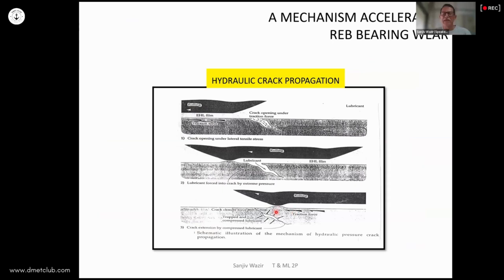But had we been using lubricants to prevent this from happening in the first place, or to extend the time before it happens, then these surfaces are now wetted surfaces, and if sufficient lubricant has got entrapped inside when we are trying to close down that crack, the trapped lubricant might create a kind of hydraulic jack effect inside that crack. The crack might actually propagate faster than had it been dry in the first place. So we need the lubricant to prevent this from happening or to extend the time before it happens, but eventually it does result in reducing the life of that equipment.